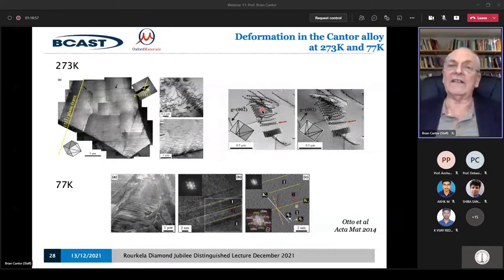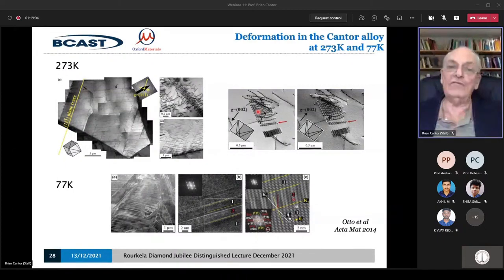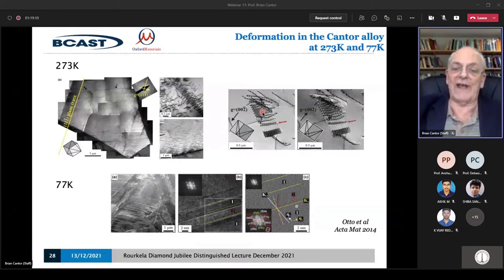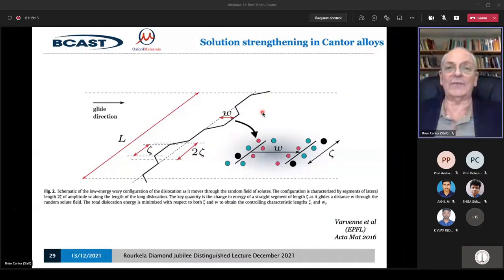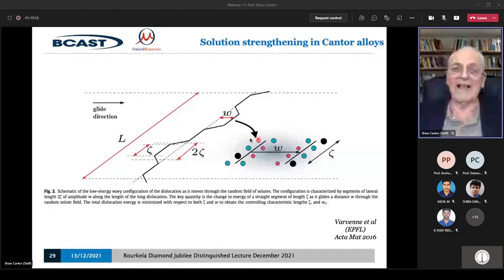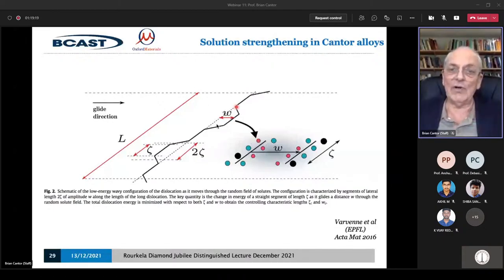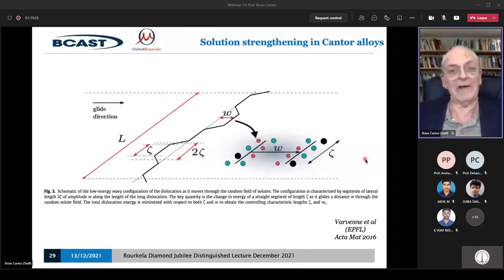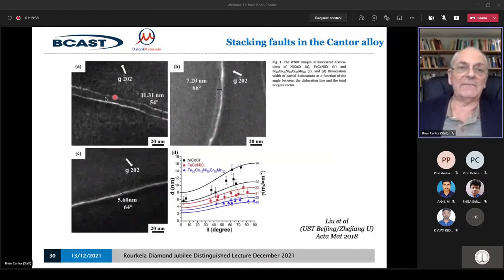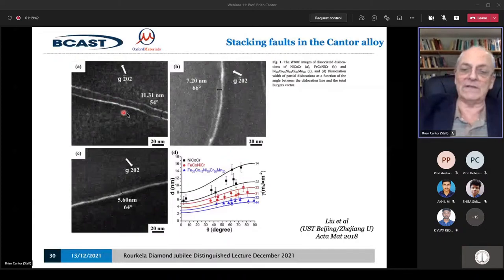So we get the same levels in the Cantor alloy of formability and of fracture resistance, but the dislocations don't move around so easily, just like the vacancies didn't move around so easily, because they have to move through the local strains in the lattice that I've already talked about. So because every atom is different in the lattice, here's a dislocation line. As it moves, it gets held back because there are local strains. That makes it have a wavy shape, and it means that they move around just as they do in pure gold or pure copper, but they do it at a much higher strength level. That's why we get the great combination of strength and ductility. Here are some pictures of some wavy dislocations to show that that is what happens.